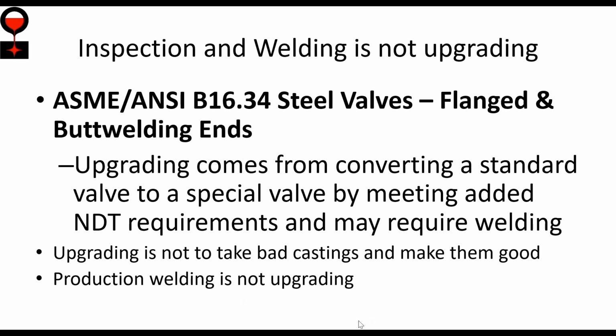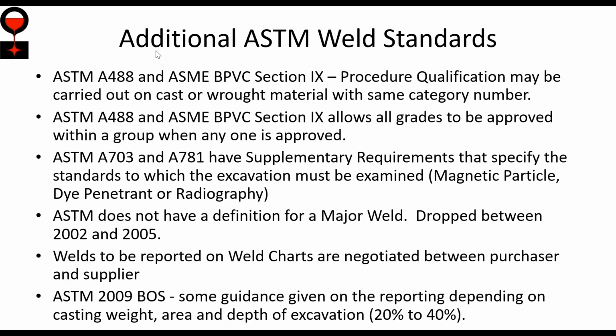Upgrading is taking a product that's already been made to a lower NDT standard, imposing a higher NDT standard, and therefore I have to do additional inspection and I may have to do additional finishing work in order to qualify it. Here's some additional thoughts for you. Under ASTM 488 or ASME Section 9, the procedure qualification can be carried out either on the cast or the mill material, the wrought material, or the forged material, because under the US or North American system, these materials that are in the same subgroup are considered the same in terms of welding.